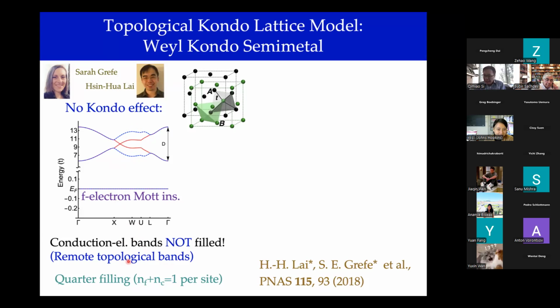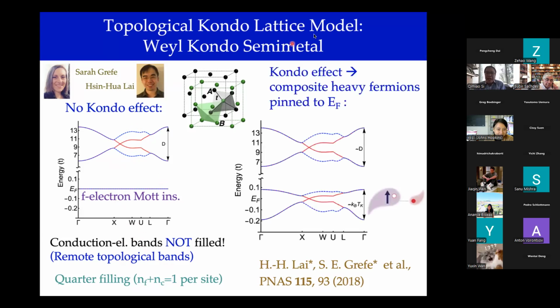However, now if I allow the Kondo effect to happen, it will generate the composite heavy quasiparticle. So this is interaction driven. These are low energy excitations. Z being 10 to the minus 3 means that these excitations are bound to the immediate vicinity of the Fermi energy. And on top of that, anything that's symmetry induced, such as topological nodes, would now be pinned to the vicinity of the Fermi energy.